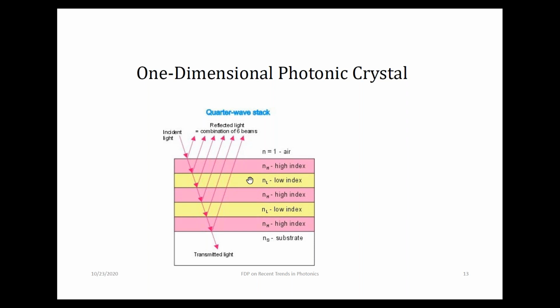We call it a quarter wave stack because, by calculation, you get a maximum or minimum reflection when each layer in the stack has a thickness of lambda by 4n, where lambda is the wavelength at which you are expecting a maximum reflection. That is why you usually make these dielectric layers as anti-reflection or high reflection coatings. If you look at the dielectric mirrors in our labs, they have dielectric coatings, specially designed to get high reflection at a particular wavelength, and all other wavelengths are not reflected. There will be a particular wavelength or a small range on which you will get almost 99 or 100% reflection. Such dielectric mirrors use the same principle.